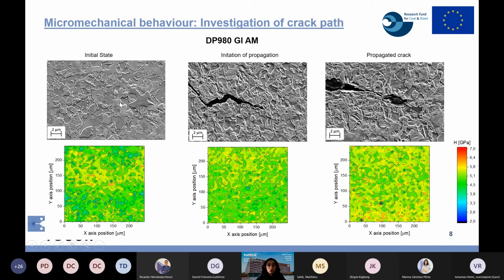Very briefly, because the microstructure has been explained before. DP, this dual phase, consists basically of ferrite, bainite and globular martensite. And it's important to note the lack of retained austenite in this steel grade. Here we can observe the crack evolution at the initiation of propagation and when the crack is propagated. And below these images, we can find the hardness mappings. We can observe how the hardness distribution evolves during the test. So we can observe basically that hardness is increased.